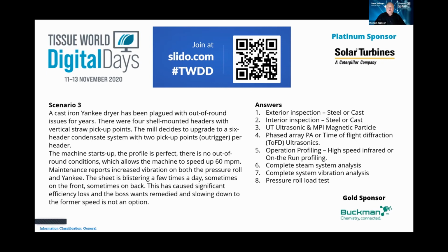The boss wants it remedied, and slowing down to the former speed is no option. Number 1 to 8 in terms of your answers. You've got 60 seconds to answer these, please. Is it exterior, steel or cast for the inspection? Interior, steel or cast? Is it the UT ultrasonic and magnetic particle, phased array, PA, or time of flight diffraction ultrasonics? Maybe it's operational profiling on high-speed infrared or on-the-run profiling, or complete steam analysis, or number 7, a complete system vibration analysis, or last but not least, is it the pressure roll load test?